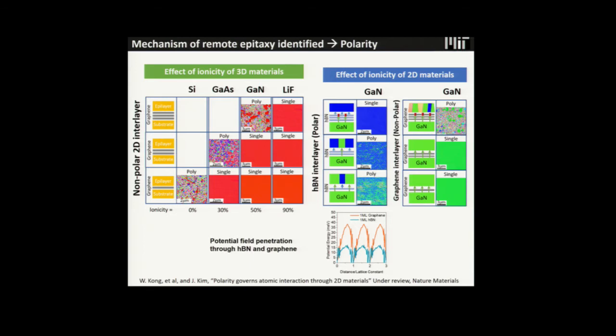But now you ask a question, does this work only for graphene? Here's an answer. We play with this ionicity of the 3D material by fixing the non-polar graphene in the middle. So now we change the polarity of the 2D material by putting in HBN, which has lateral polarity of the bonding. As you can see, it's not as transparent as graphene. We performed the epitaxial growth of gallium nitride on monolayer boron nitride on gallium nitride. As you can see, it's really interesting.